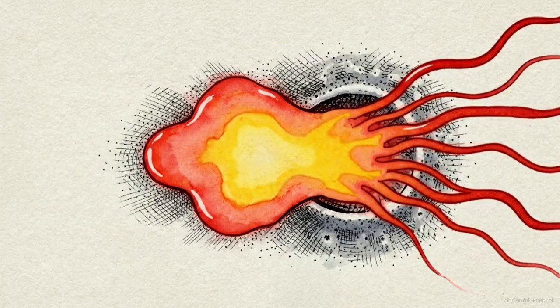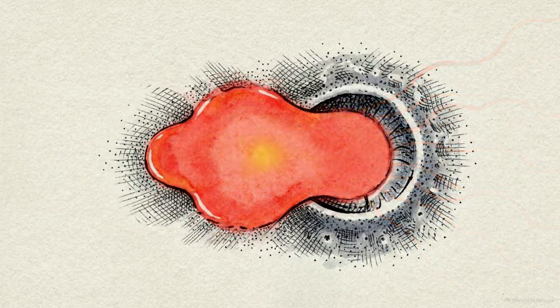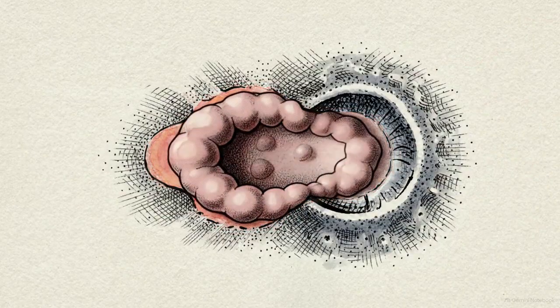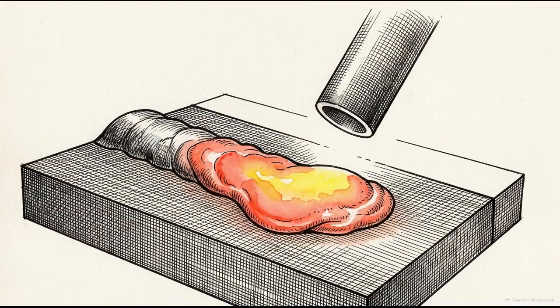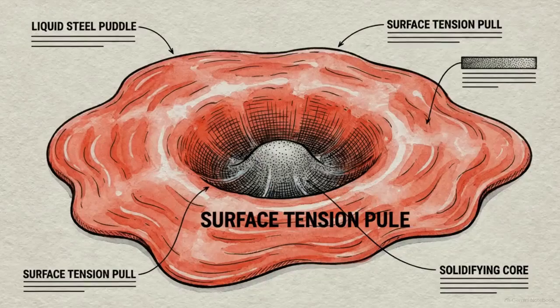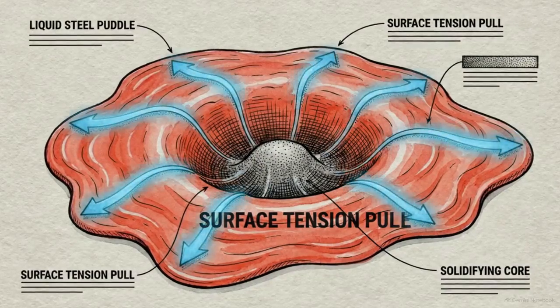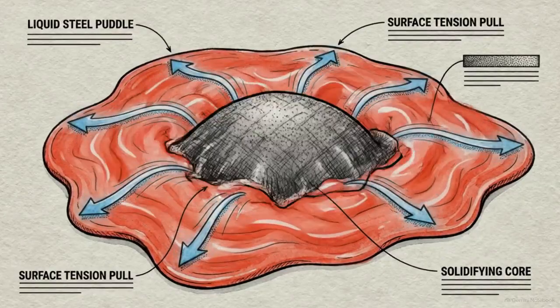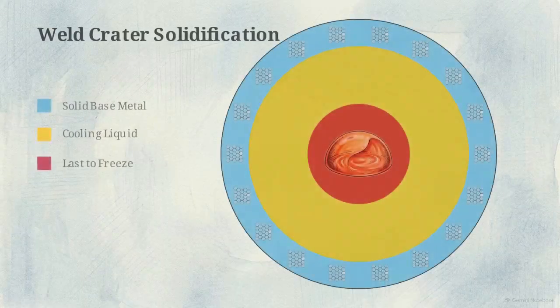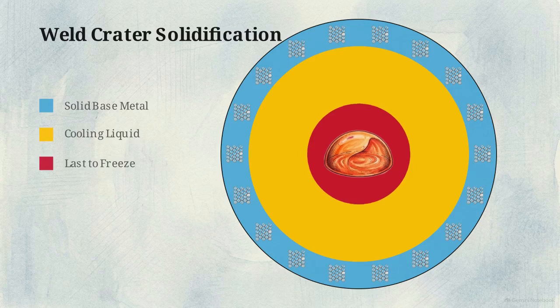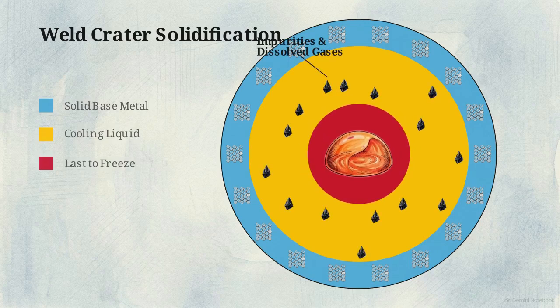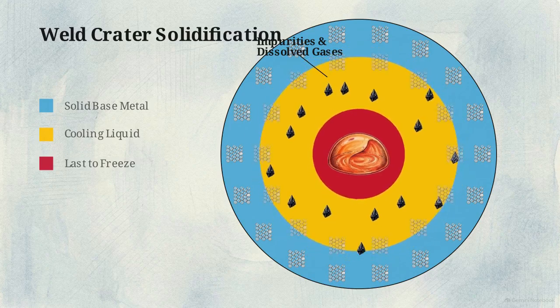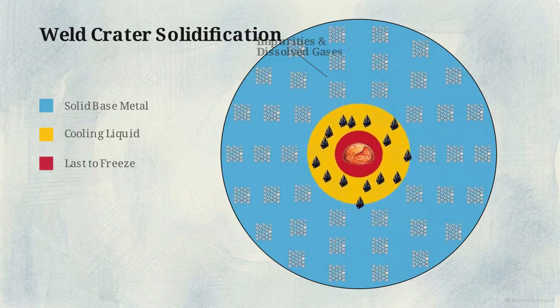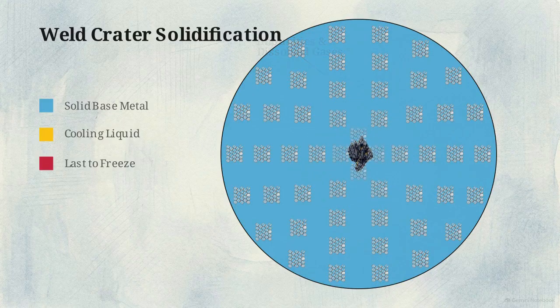We see the culmination of these physics in the exact moment the welder breaks the arc, removing the electrical heat source. Without the steady deposition of new filler metal to feed the puddle, the liquid steel is subjected to intense surface tension, pulling the cooling edges outward and leaving a dimpled crater. This thermal heat map shows a top-down view of the crater. Because edges cool first, the dead center is the last microscopic volume to freeze. As surrounding metal solidifies, remaining chemical impurities, dissolved gases, and shrinkage stresses are pushed inward, concentrating into this final vulnerable zone.